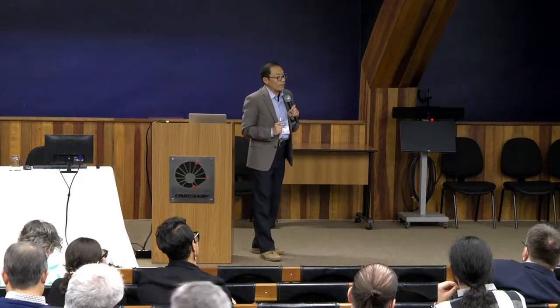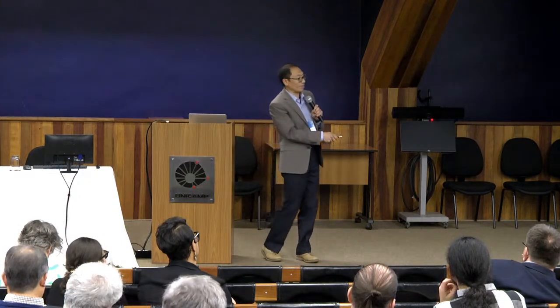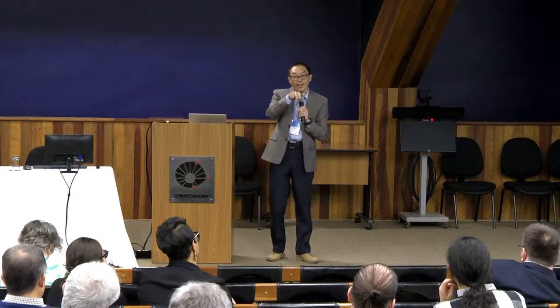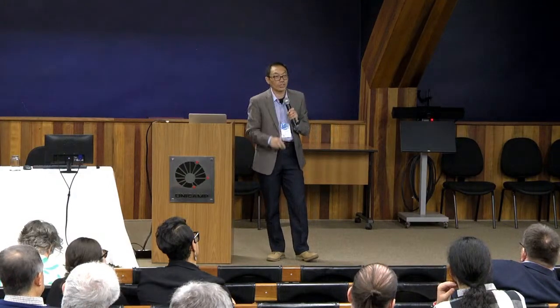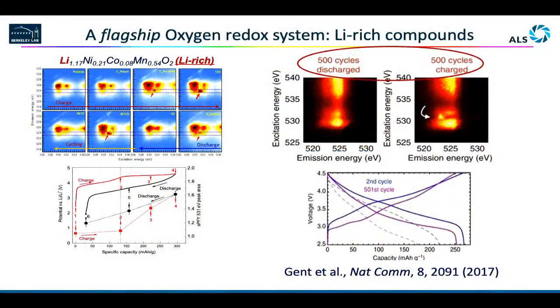However, there's another issue I just mentioned previously on the hysteresis of the voltages. Lithium-rich compound, however, unfortunately, have that issue also. You will see the charge and discharge curve. They are well separated, and the killing factor to commercialize this material after almost two decades of effort is actually the voltage drop. It's not the capacity. It's actually the voltage drop. That's a killing factor for industry because it's not only the